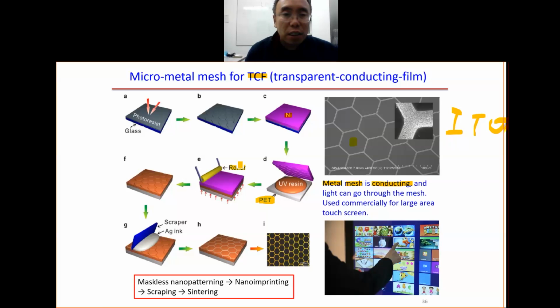This is for the commercial application. We do the roller imprint to roll the mold. You make sure you have good contact between the mold and the substrate. Then you shine the light and you get the pattern here. Then you put in the silver ink, silver nanoparticles. Then you do the scraper.